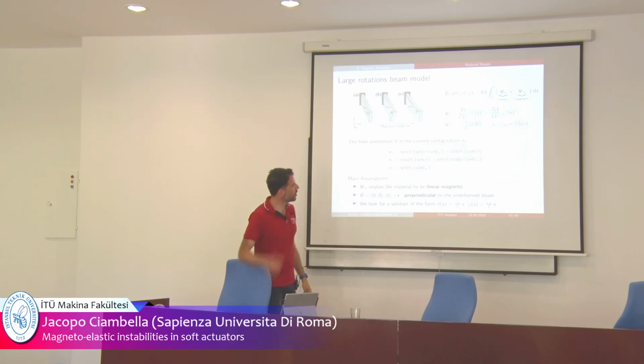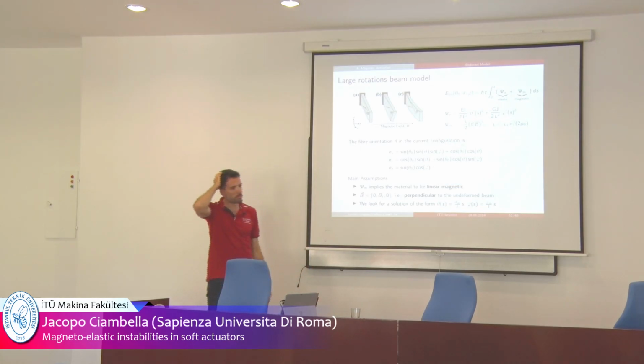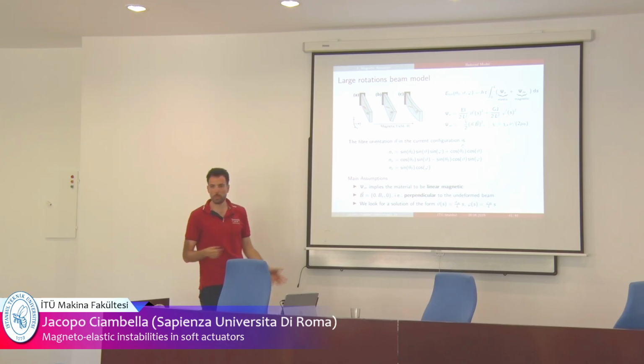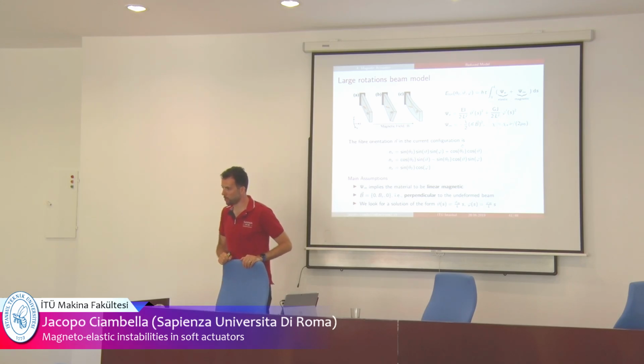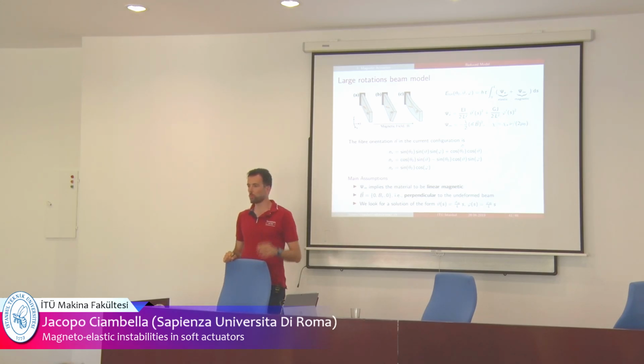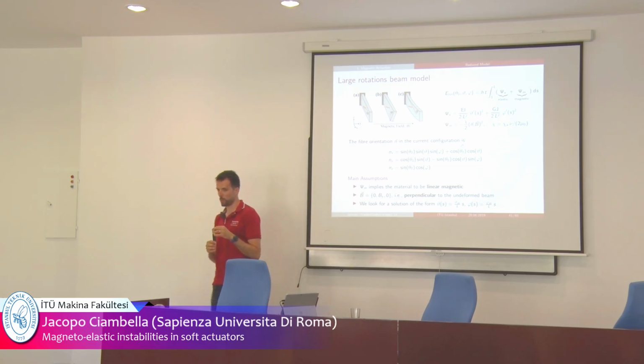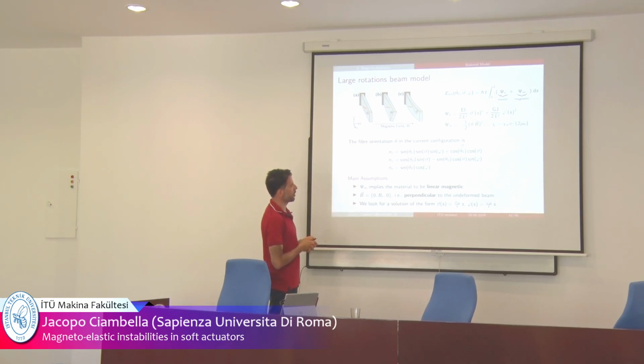And why so? Then we try to interpret these results with a simple model. So the specimen is actually a very thin specimen, so we use beam theory, large strain beam theory. We didn't need to do 3D nonlinear elasticity, because these are very thin strips, so they can be well described with the beam theory. In the beam theory, you have an elastic energy, large strain beam theory, which depends on theta prime, which is